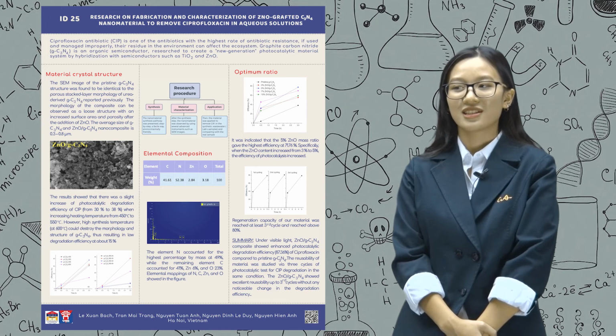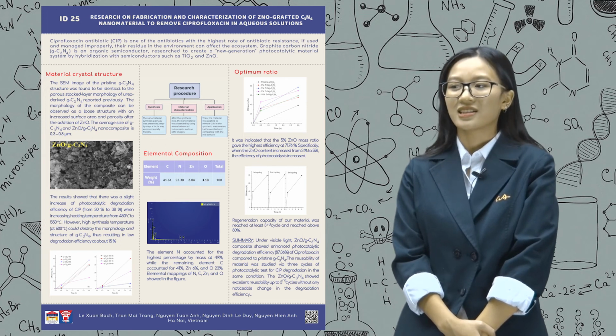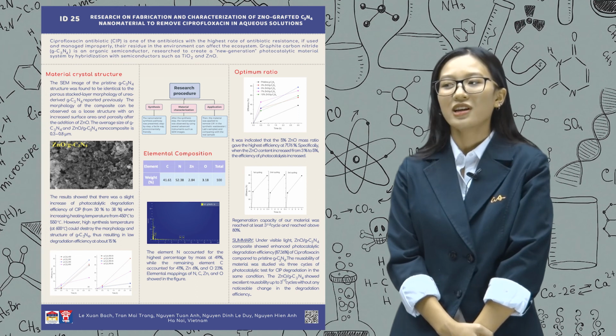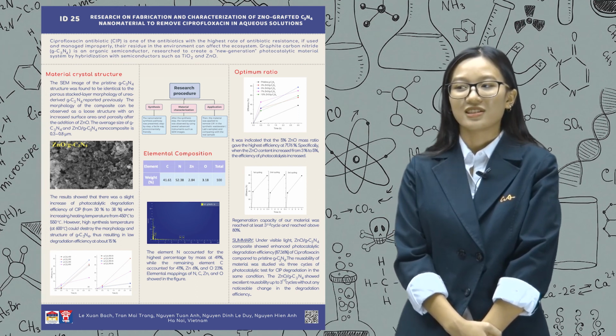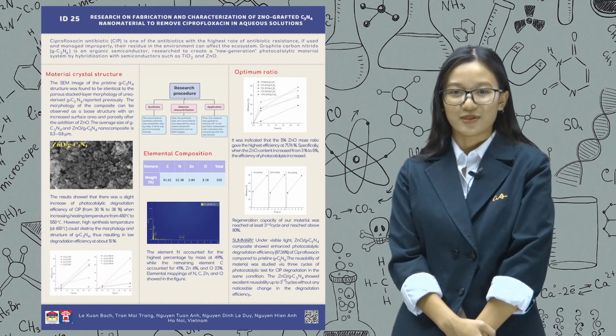The reusability of the material was studied via 3 cycles of photocatalytic tests for CIP degradation under the same conditions. The zinc oxide/g-C3N4 shows excellent reusability up to the 3rd cycle without any noticeable change in the degradation efficiency. That's the end of our presentation.